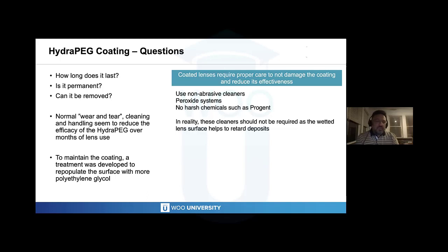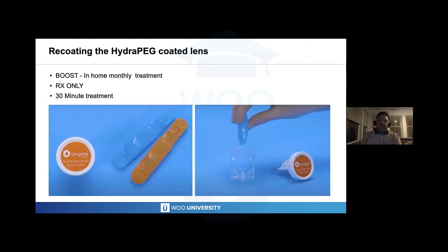It is important with the HydraPeg coating that we use approved cleaners. We're not going to use abrasive surface cleaners. We're going to stick to non-abrasive cleaners, peroxide-based systems, and not use any harsh chemicals for cleaning, such as Progent. And of course, harsh cleaners, abrasive cleaners, harsh chemicals shouldn't be needed because that surface coating is going to keep the lens, in theory, from building up deposits so significantly. So there should be no need to use these strong cleaners and abrasive cleaners on a lens that has the coating.